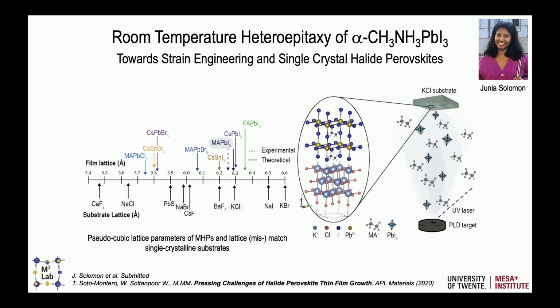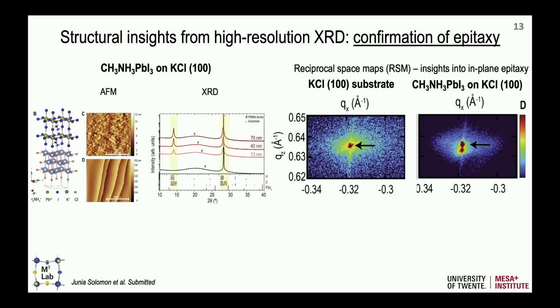So in this paper, we also summarize some of the substrates that you can use. For example, potassium chloride with a lattice of 6.3 angstroms matches really well the cubic phase. Well, not very well, there's a little bit of a shift, but in the case of MAPI. So the idea is you have a cubic substrate, and then you put a cubic perovskite on top. And of course, that was a hypothesis, but then Junia came to start in the group. She's also here, and she had a poster, and she had that challenge to demonstrate that it was possible. So we use PLD. We use a target of methylammonium lead iodide, and then she controlled the growth to actually show we can do this epitaxy.